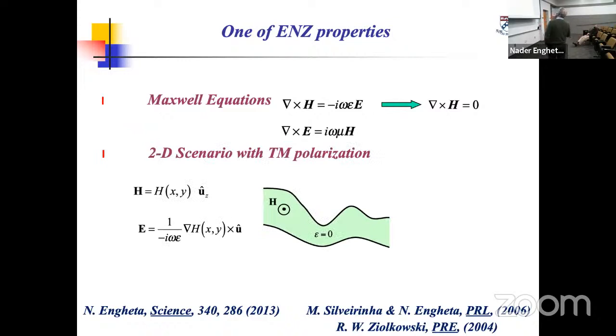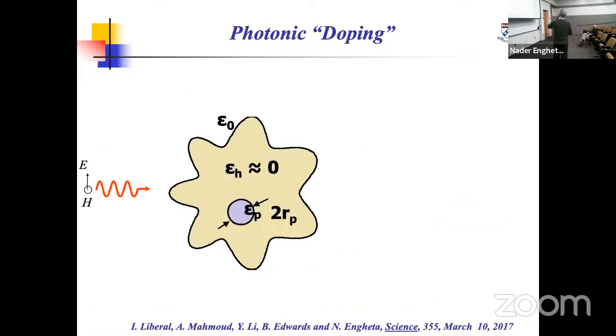One of the interesting scenarios is that inside the ENZ material, if you have epsilon near zero, obviously curl of H is equal to zero. If you look at the case of a polarization with the magnetic field coming out of the screen and the electric field in the screen, the TM polarization, then you can prove that for this case, the magnetic field has to be uniform along this ENZ. Now, that has a very interesting consequence. That means that if you start with a column of ENZ with arbitrary cross-sectional shape, and put a dielectric rod inside of this, anywhere you want,